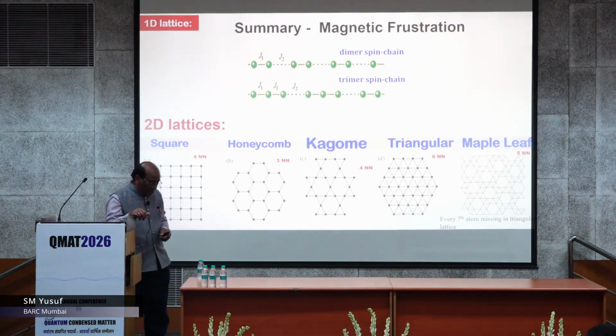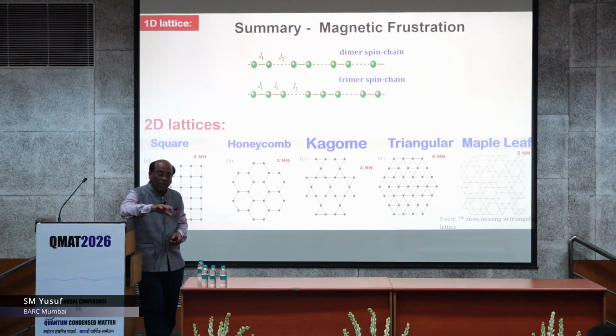And as I said, when this frustration, along with the low spin value and the low dimensionality, these three are a very dangerous combination to see the quantum properties, which are manifested even at very high temperature, even as high as very close to room temperature.